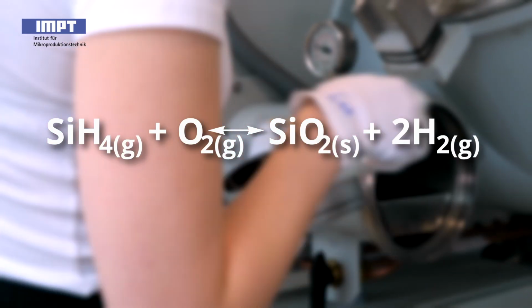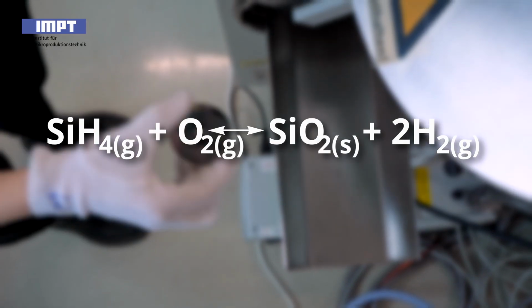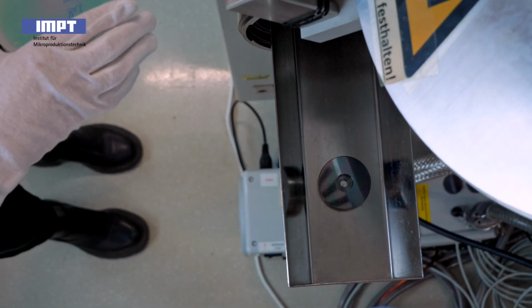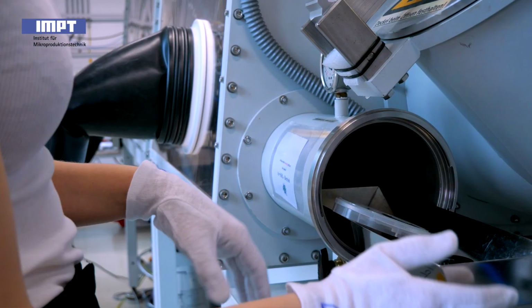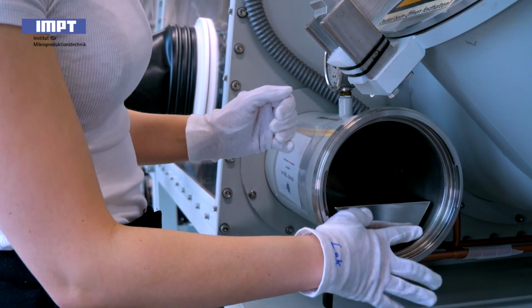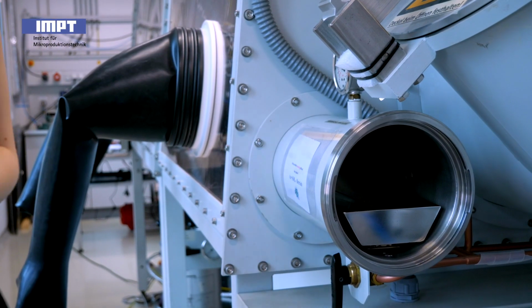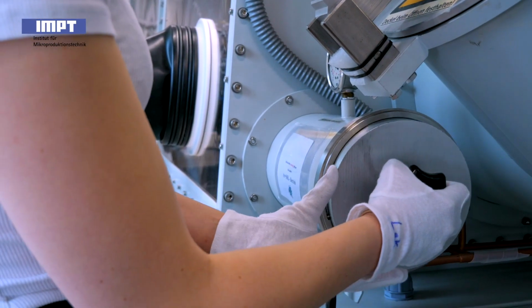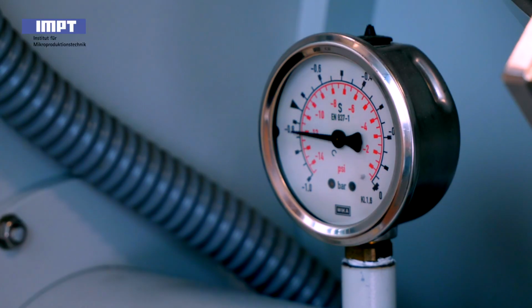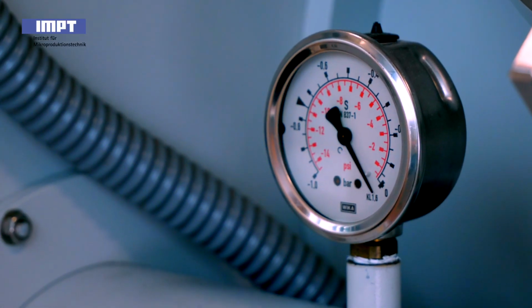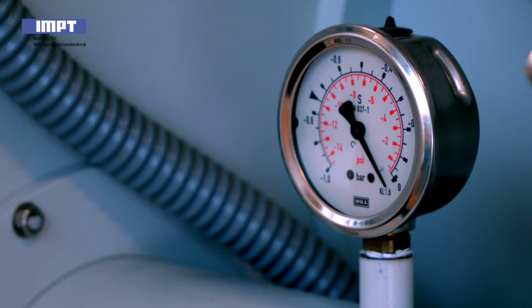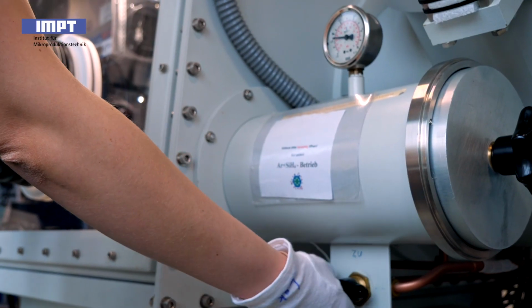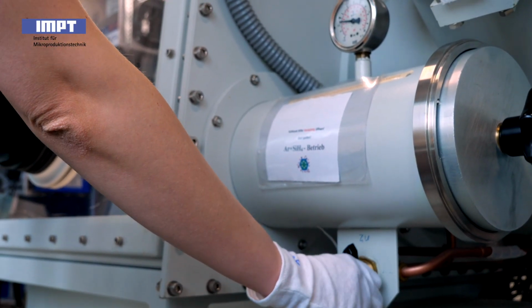The reaction between silane and oxygen in the inert gas produces an oxygen partial pressure of less than 10 to the power of minus 23 bar, achieving a practically oxygen-free atmosphere at ambient pressure. This environment approximates an extremely high vacuum, similar to the conditions found in outer space. This is why we talk about an extremely high vacuum adequate atmosphere in terms of the oxygen content.